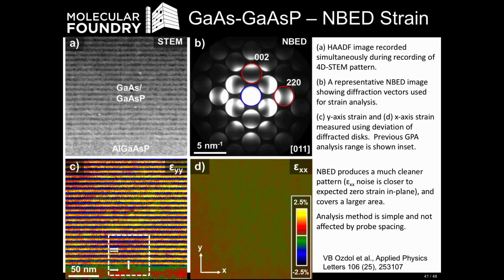And so once we verify that there's no in-plane strain here in D, we could even change the dimensions of our scan, and we could scan through the entire film. We could do a micron along the growth direction and maybe make it only 20 nanometers wide, for example. But of course, the first question you might have is, is this as accurate as the conventional atomic resolution strain map?